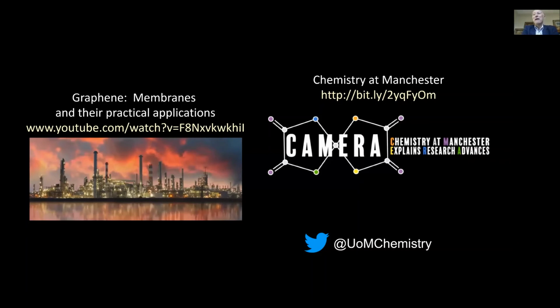If you want something that is highly conductive, then graphene has extraordinary electrical conductivity. But it's actually in competition with indium tin oxide. But indium tin oxide you can't make into flexible things. Graphene potentially you can, which is its advantage. But now other materials are coming along which will potentially compete with graphene. So in any application, there is always competition. And of course, for every materials chemist trying to push one material, there's another materials chemist trying to do better with a different material. And which wins out at the end of the day depends on a whole range of things.